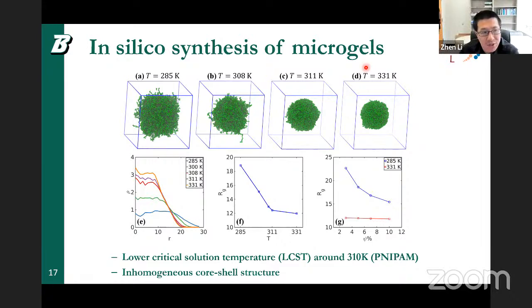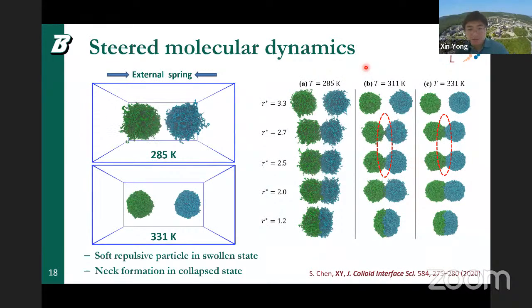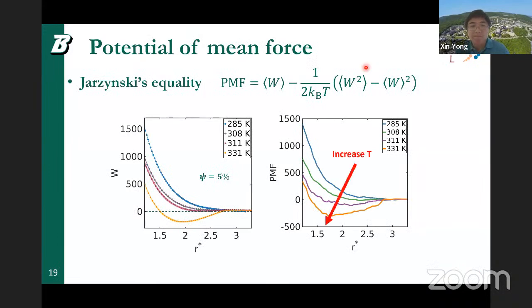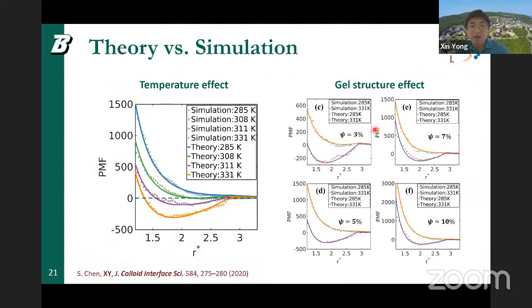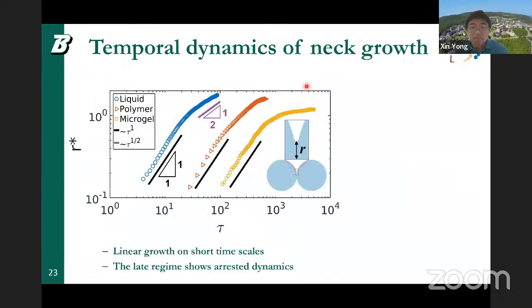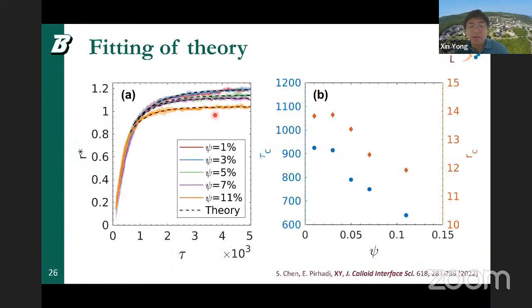So have you tested the rigidity or elasticity of the microgel? Yeah, that's a great question. We didn't directly test the mechanical property, but from these interaction potentials, as you can see here, there's a significant change in the repulsion region as well as the neck growth. This will reflect the change in the elastic property of the network itself. But in short, we didn't get a chance to really measure G prime and G double prime.